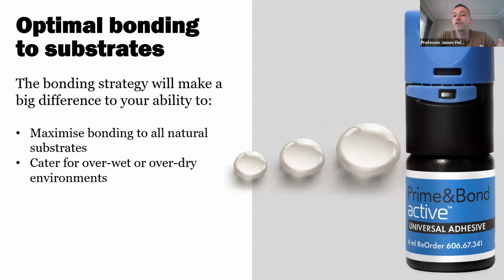And we've known for a long time in a lab that the traditional three-step approaches, etch, prime, and bond, are the most predictable and robust ways to employ bonding strategies. But actually in the clinical environment, they become some of the most technique sensitive ways and therefore aren't implemented particularly effectively. And we turn to simpler systems, which in theory will have slightly less bond strengths and inferior bonds, but actually clinically outperform because they're less technique sensitive, they're easier to use, and people tend to cut fewer corners or have fewer complications with using those materials.